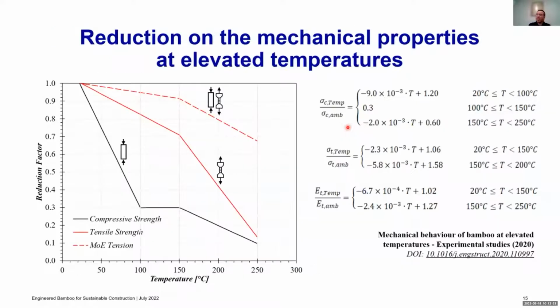So with all that information, we ended up building a reduction factor for the effects of temperature. So this is the normalized property. It could be normalized compressive strength, or the normalized tensile strength, or the modulus of elasticity. In this case, this is the change in the compressive strength. This is the reduction of the tensile strength. And here with the dashed line, you see the reduction in the modulus of elasticity. And here you have the equations to quantify that reduction factor as a function of temperature.